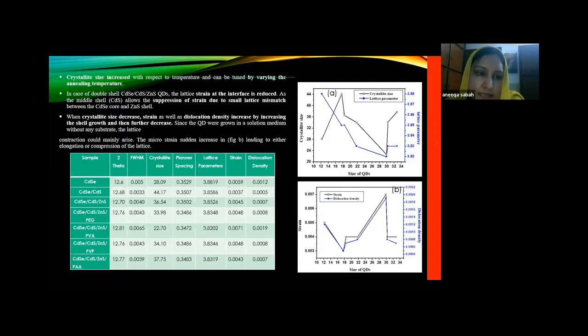When crystallite size decreases, the strain as well as dislocation density increase with increasing shell growth, and then further decrease. Since the quantum dots were grown in a solution medium without any substrate, the lattice contraction could mainly arise, and the microstrain suddenly increases, leading to either elongation or compression of the lattices.